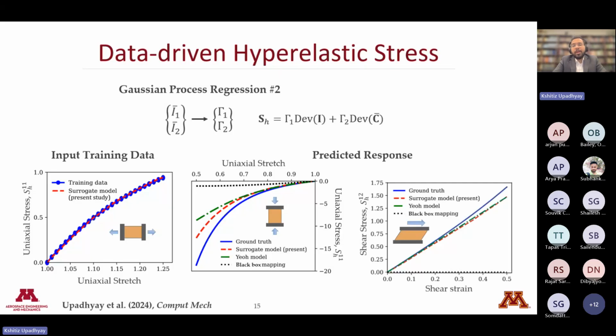We also tried to evaluate the predictions of our model in shear. So shear is a completely different deformation mode now. It is not even uniaxial. And so in shear, we see the predicted responses by the surrogate model and the Yeoh model are very close to the ground truth. So they are both doing very well. So the surrogate model is working like an analytical model with all the benefits of machine learning.